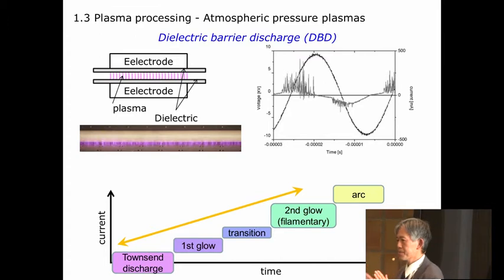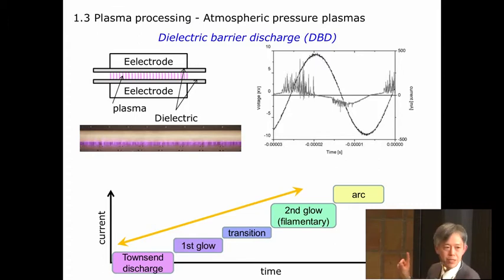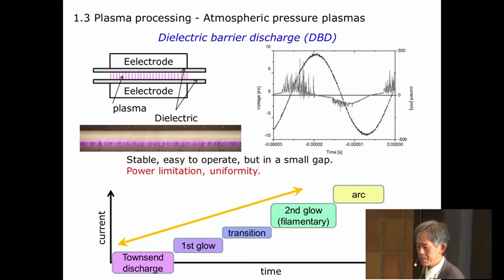Applying alternating current power to two electrodes but having the insulating plate in between so that you can block DC current, so that too much heating of the plasma can be avoided. It's a really robust technique, and probably it is the most widely used atmospheric pressure plasma source. And it is very stable. But one problem is that you can generate this kind of plasma only in a tiny gap, only several millimeters.